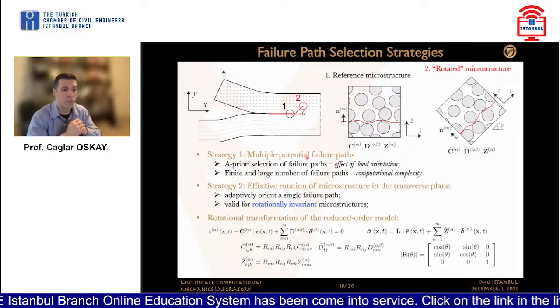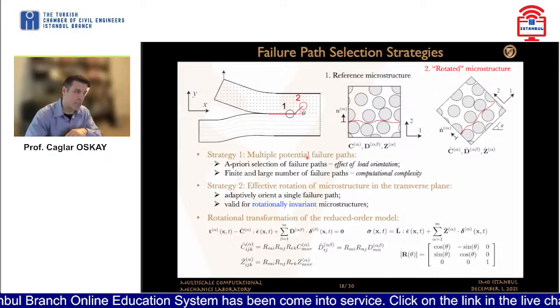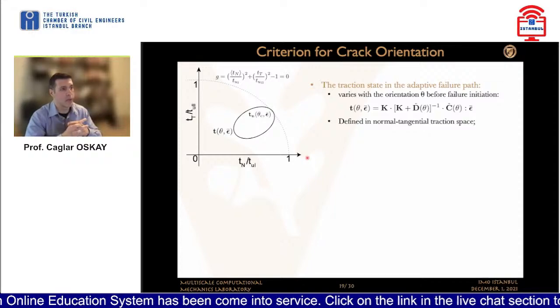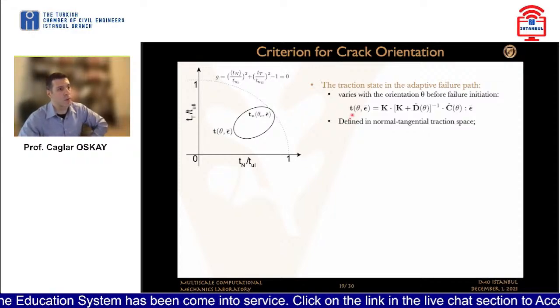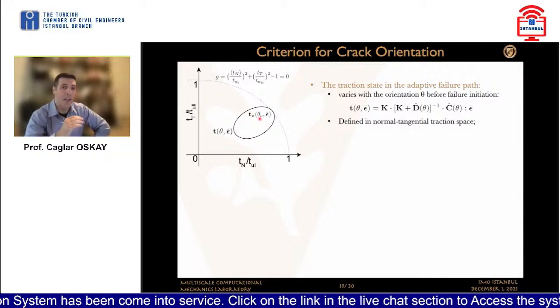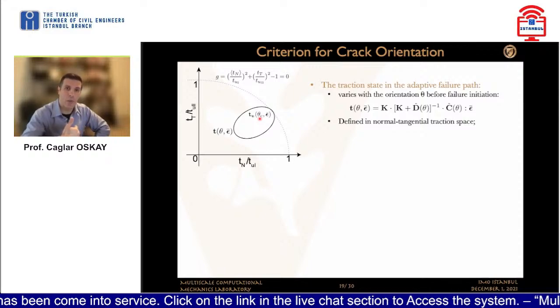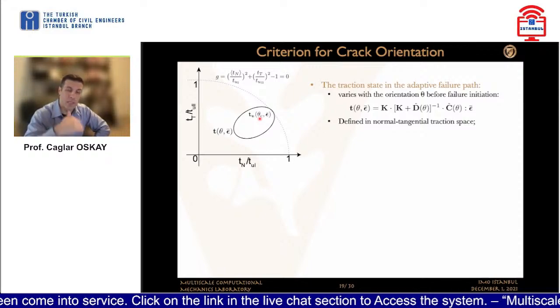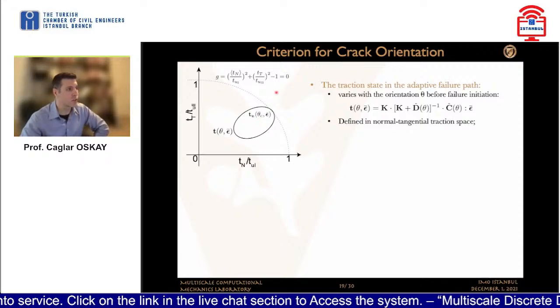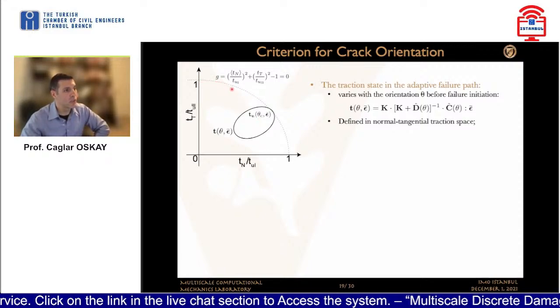And that could be a very simple transformation of the reduced order model to the appropriate orientation. So there are two pieces of that puzzle. One is the expression of the traction as a function of the orientation of the crack, and then define at which point the crack will nucleate so that we can assign the correct orientation to a given material microstructure. For that, we need to incorporate also a failure criterion.